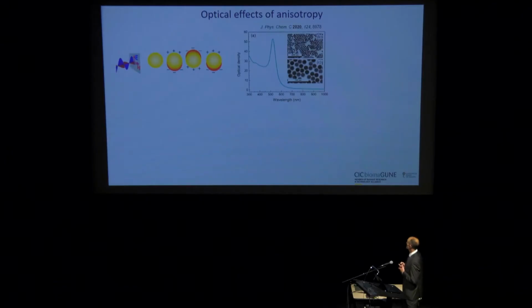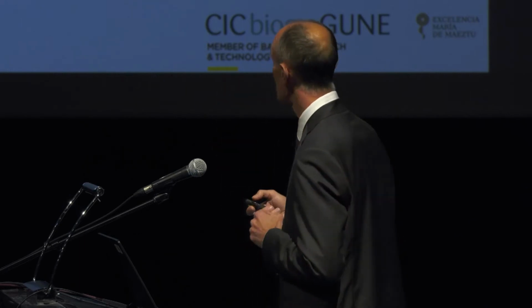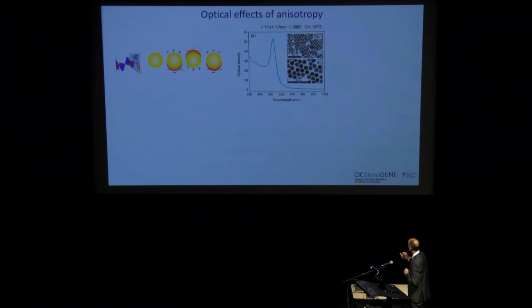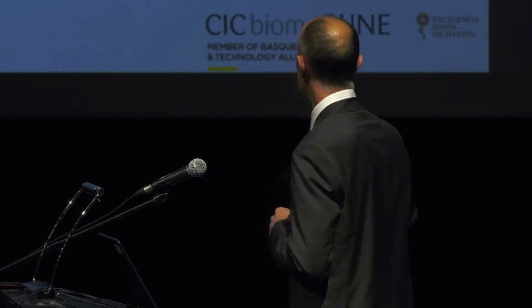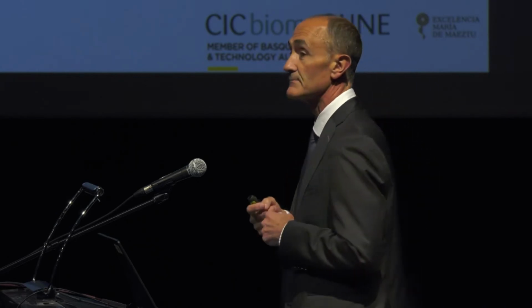And so I mentioned already that when you have very tiny particles, you can get these very sharp absorption bands when the oscillating electric field couples with the oscillation of the dipoles. When you increase the particle size in spheres, what you see is actually that this band is shifting toward higher wavelengths, red shifting, and it also becomes broader, and this is because the coupling efficiency is hindered when the particles become closer to the wavelength of light.